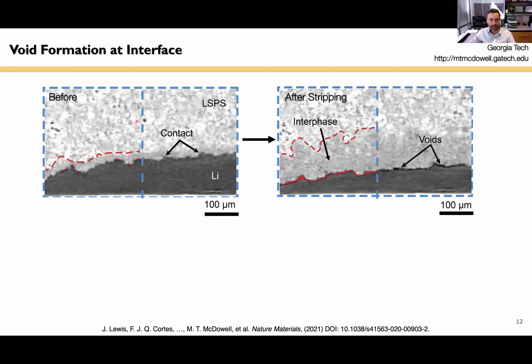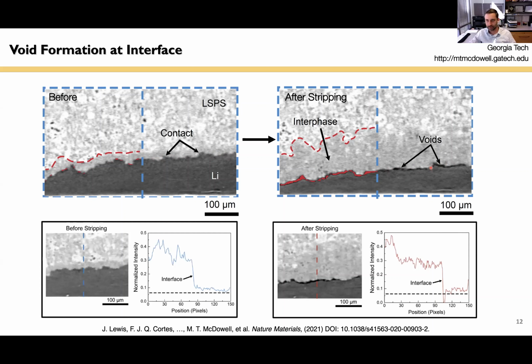So this is just another set of two images, the same location in our battery cell now. This is before stripping the lithium, and this is after stripping lithium. You can see before, even though we have a rough interface, there's fairly good contact at the interface. There's not significant contrast changes that would indicate voids. But after stripping, the same location, you can see that you have these dark spots at the interface, and these are voids, lack of material. And just as an illustration below, what we were able to do is we created these algorithms to go through all of our three-dimensional data and segment out the different phases, including the void phase, which has a very low intensity.